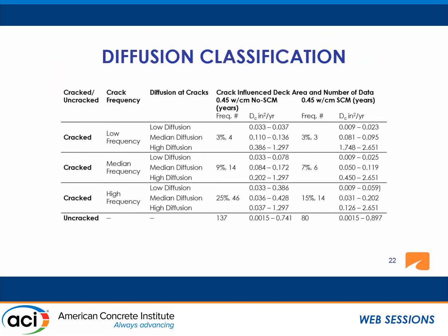In order to incorporate the influence of cracking in the service life design, rather than do this bridge by bridge, since we didn't have enough parameters from each of those bridges, we combined them into different ranges. So we did this for 9 different cases. We had 3 cases for the crack frequency, the amount of cracking: low, medium, and high. And for each of those, we have different types of diffusion, because we found even with a few cracks, you could have a high, medium, or low amount of diffusion based on the dimensions of the cracks themselves. So we have 9 cases in total.